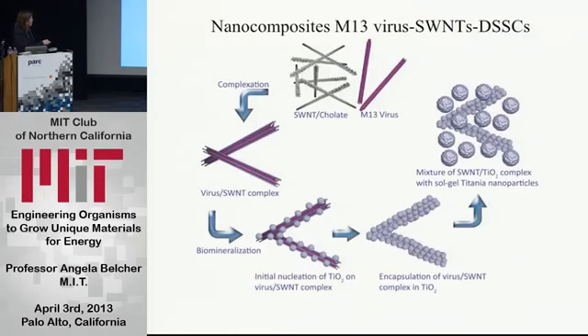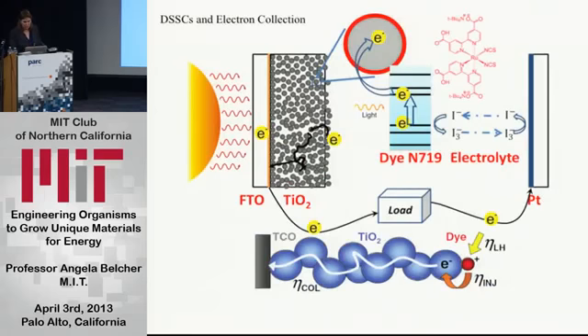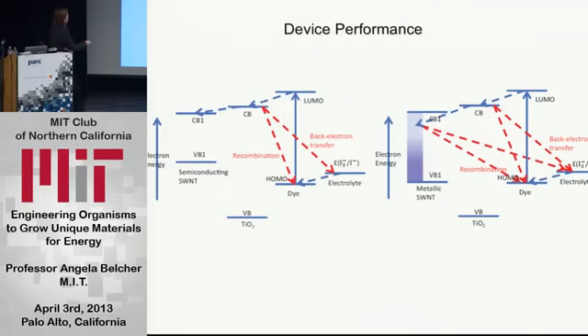Now you can take those and put them into an already existing titania nanoparticle complex that's made naturally. And you can put 0.1% biology into this system, and you can increase the efficiency of your solar cell. And so here's what we did. So now in here we have 0.1% virus-based CNTs that are growing titania in this already existing matrix. And what happens is, again, here's your electrolyte, here's your dye. Your electron is transferred to the titania, and then it can be transferred directly to the carbon nanotube, and you get less back electron transfer and back recombination, and so you should be able to increase your efficiency.